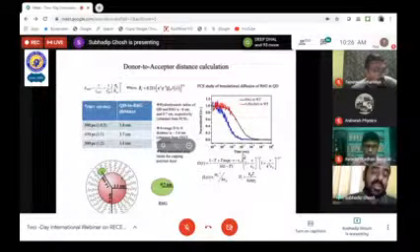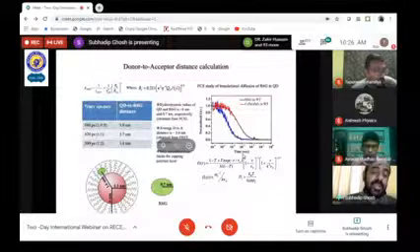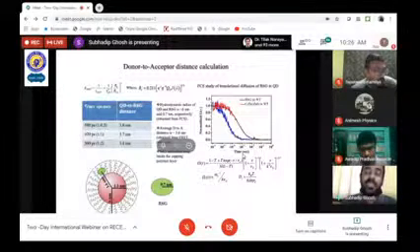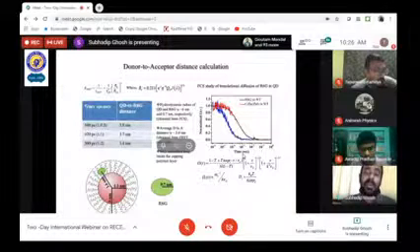Fluorescence correlation spectroscopy is a single-molecule method, and from this curve, after treating, we can get the translational diffusion time of the molecule. Then, using the Stokes equation, we can get the diffusion constant, and from there we can get the size of the molecule. Here we get the size of the molecule, and we also found the length of the capping agent, with a hydrodynamic length of 6 nanometers.